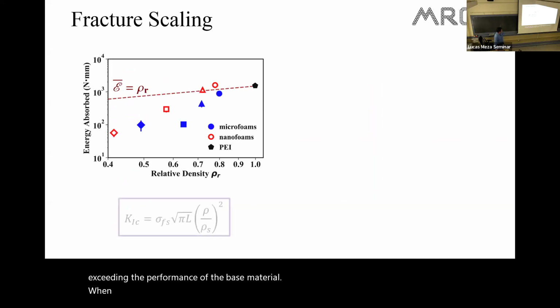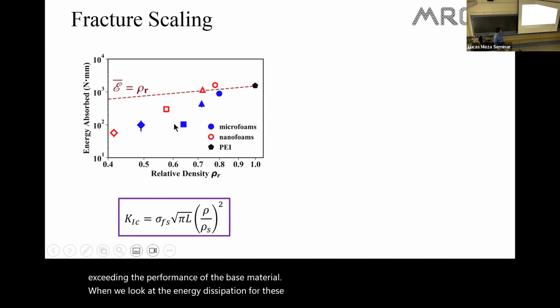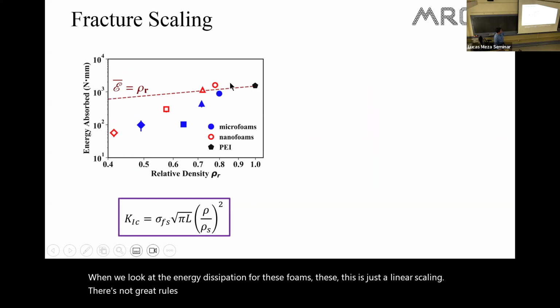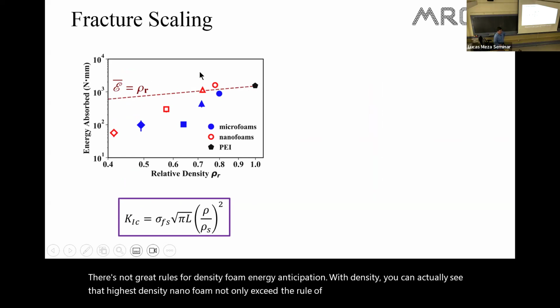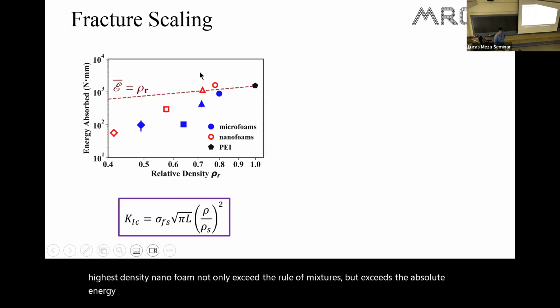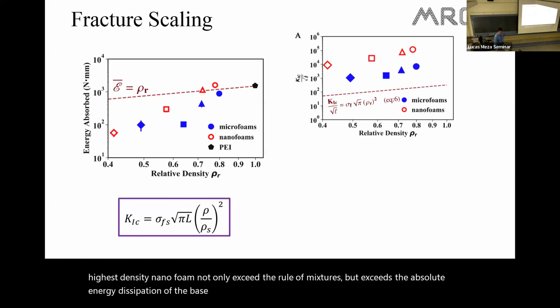When we look at the energy dissipation for these foams, this is just a linear scaling. There's not great rules for foam energy dissipation with density. You can actually see that the highest density nanofoam not only exceeds the rule of mixtures, but exceeds the absolute energy dissipation of the base PEI material.